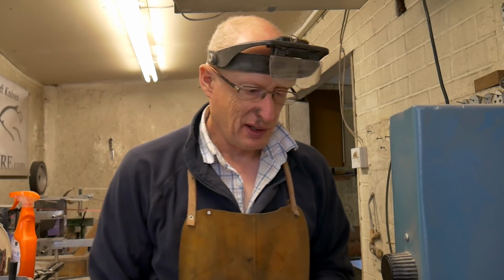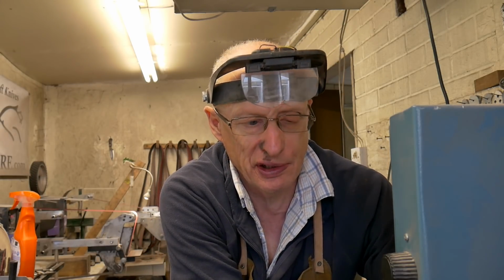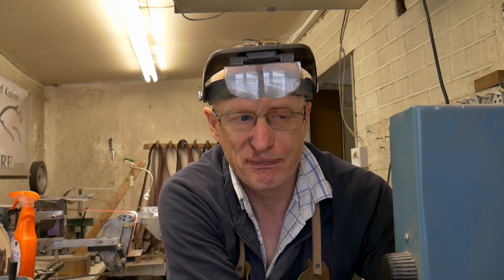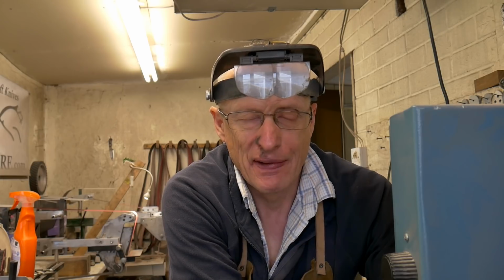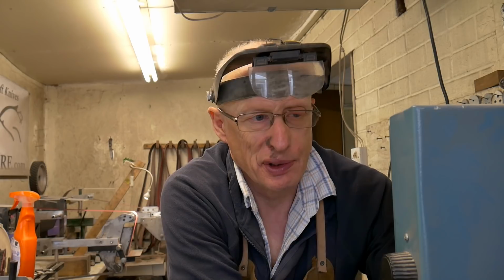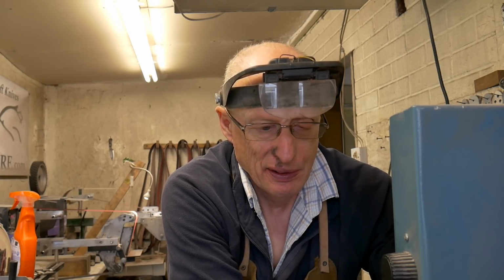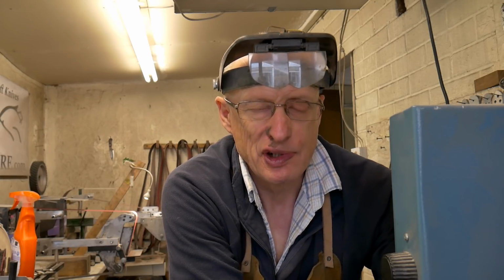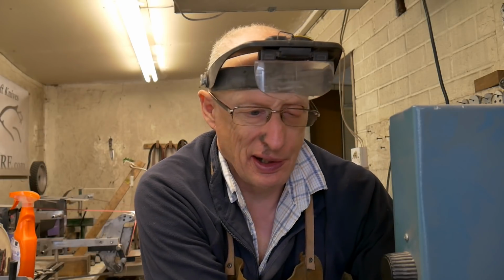But if you had really overheated your knives and you'd caused grain growth, or if you had retained austenite, it's still possible to get a 59 HRC reading and still have a knife that isn't any good. So there's a way you can be absolutely sure, and it's dead simple, and it's very destructive.